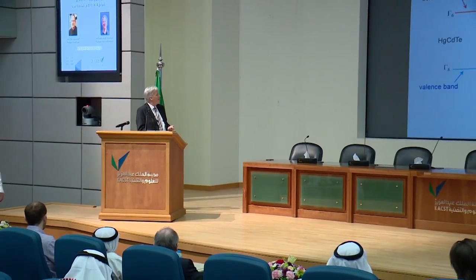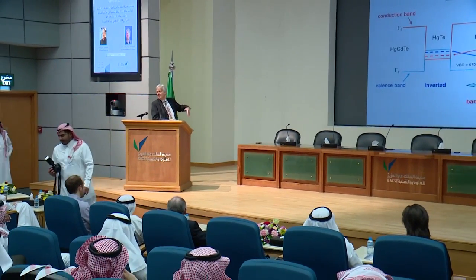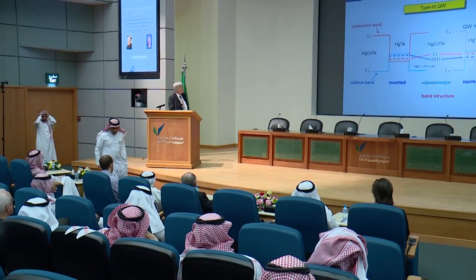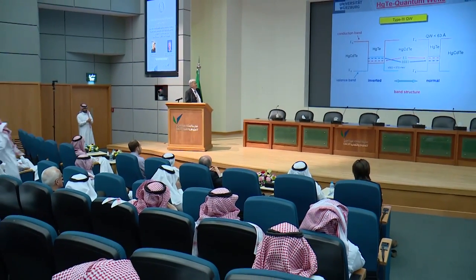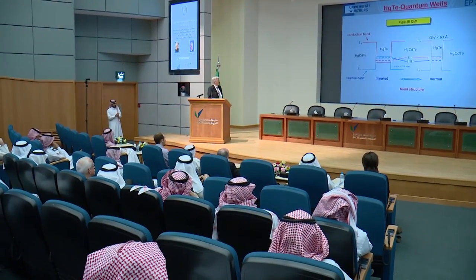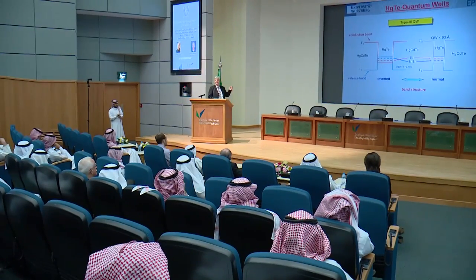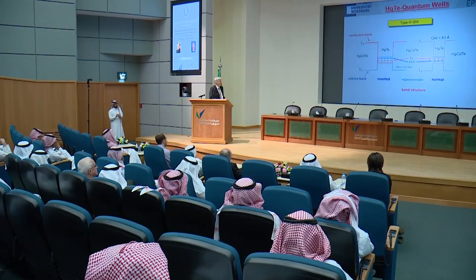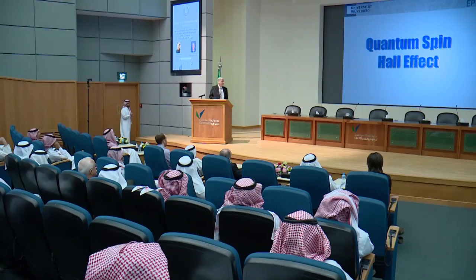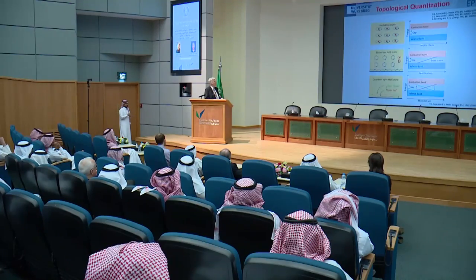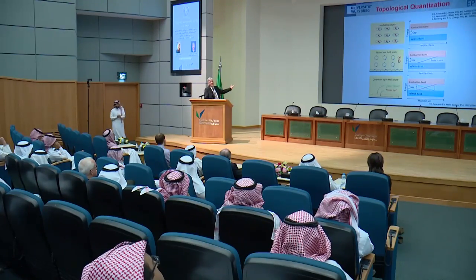But if you now narrow down your quantum well and you add confinement energy, basically what you do is you push down the H state and you push up the E state, and there's a critical thickness where these guys overlap. And then for narrow quantum wells, the E state is above the H state, and you have a normal band structure again. And so basically, by tuning the width of your quantum well, you can tune the material from being topological to normal. And that already gets us into this first effect that we looked at to see these topological insulator things. And this is where it all comes from.